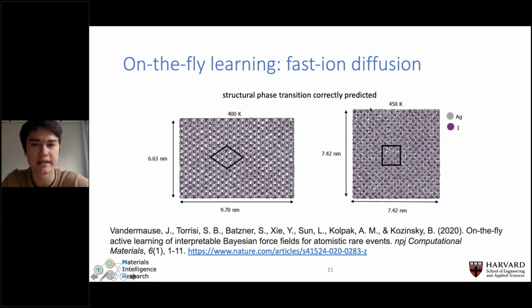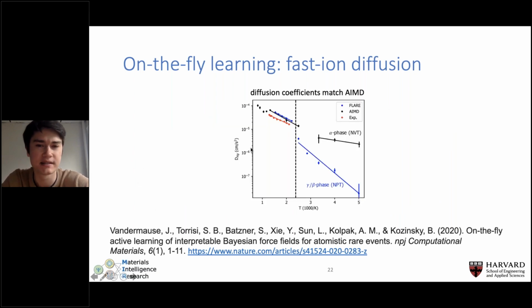Above 420 Kelvin, we get this nice cubic BCC phase with the silvers sort of zipping through the material. Below 420 Kelvin, we have this hexagonal close packed phase where nothing terribly interesting is happening. The silvers are kind of locked down in the crystal. And so the ultimate test is how well do the diffusivities of the silver compare to both AIMD and experimental values.